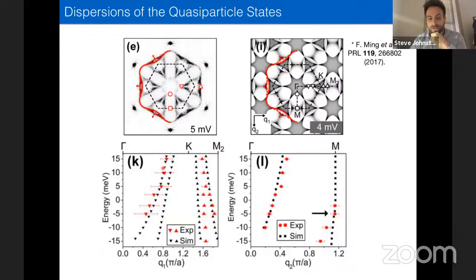So the red dots are the dispersions of the experimental features, and the symbols correspond to the same features here and here, here and here, circle and here, and then the square and here. And then the black dots are what we get out of the corresponding simulation. Again, I want to remind you that I have not adjusted any band structure parameters in this calculation. I've simply taken the band structure predicted by DFT. I've adjusted the chemical potential to give me the filling that we think is in the system, and then just calculated it as a function of bias voltage. And we can roughly reproduce a lot of the dispersion that we're seeing. There's some deviation here. Yeah, go ahead.